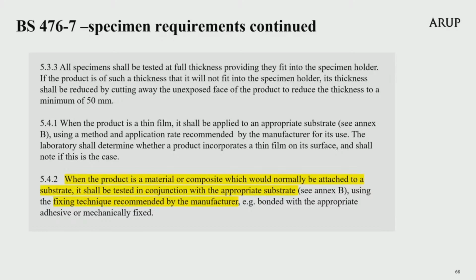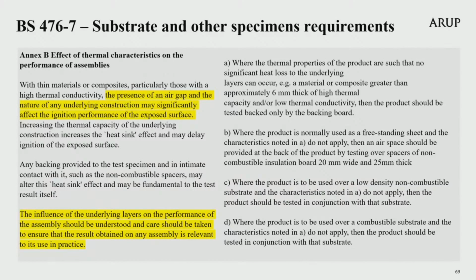When the product is a thin film, it shall be applied to an appropriate substrate using a method and application rate recommended by the manufacturer. The lab shall determine whether a product incorporates a thin film on its surface and shall note if this is the case. When the product is a material or composite, which would normally be attached to a substrate, it shall be tested in conjunction with the appropriate substrate, also using the fixing technique recommended by the manufacturer. Please note the significance that this standard makes to the effect of the underlying substrate, and the reader is referred to Appendix B of Part 7 for more information. Part 7 also provides a clear explanation regarding the impact of any underlying construction on the ignition performance of the surface. This test standard again provides rules on how the sample should be tested as a result.